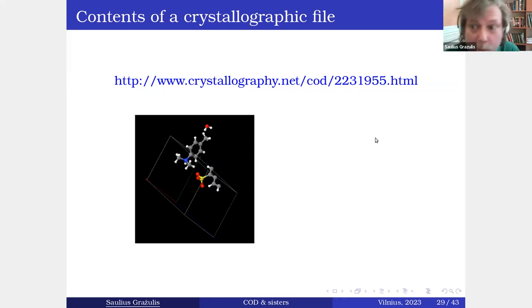And it's very important for practical processing of crystal data, because if you look into a crystal structure like I've shown here, you will see that some molecules are not represented in whole. There is just half of or part of the molecule in the file. And this is because the crystallographers only describe the so-called asymmetric unit of the crystal. And then you need to apply crystal symmetry operations that reconstruct the remaining part of the chemically connected atom net, or the molecular entity, as we call it.